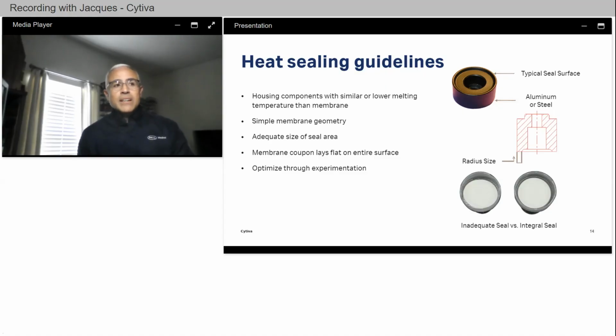Next, note that an adequate seal area width is important. We recommend widths ranging from 50 to 125 thousandths of an inch. The coupon should lay flat on the entire surface when sealing is to occur. Sealing areas that cause the media coupon to dome or wrinkle will not produce a consistent, reliable edge seal. Cycle times with this method should be monitored and not exceed 1.5 to 2 seconds to avoid damaging the membrane's working filtration area.